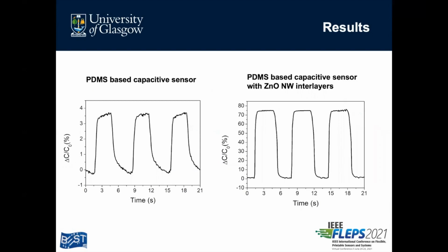After studying the sensitivity, we also assessed the two samples' reliability by carrying out a cyclic loading test by loading and unloading the sample using 1 Newton force at a frequency of 0.33 Hz. As you can see, the sample with zinc oxide nanowire interlayers on the right-hand side shows a full recovery response, less noise, and a larger range of capacitance change by a factor of around 21%, which indicates a higher stability and reliability compared with the PDMS-based capacitive pressure sensor.